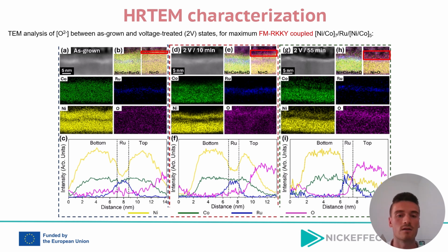As a further characterization study, high resolution transmission electron microscopy analysis probed the oxygen distribution in the as-grown and voltage-treated states of the static composition multilayer. The elemental maps and density profiles show how oxygen diffuses into the structure over time, with panels A to C showing the as-grown state, D to F the gated state of just 10 minutes gating, and G to I the gating state of 2 volt, 55 minutes. It's clear that the oxygen signal in purple increases and spreads into the top nickel-cobalt layers with increased voltage application time, while the ruthenium in blue remains localized. These observations support the voltage-induced oxygen migration process in the static multilayers.